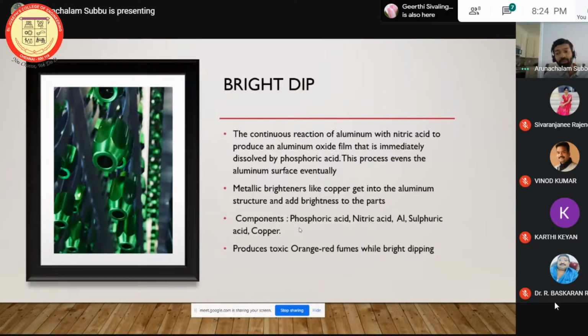Yeah, the bright dip. So the bright dip, we do this to get a brighter color. So what is the bright dip? The solution is a mixture of phosphoric acid, nitric acid, and copper. The phosphoric acid and nitric acid remove the top layer of the aluminum, and it makes sure that the copper enters the aluminum surface. The copper adds brightness to the parts. This step is done in the pretreatment side, and then we do anodization later, and then we apply the dye, and then we seal them. So the bright dip is just the polishing step that you do in the pretreatment.